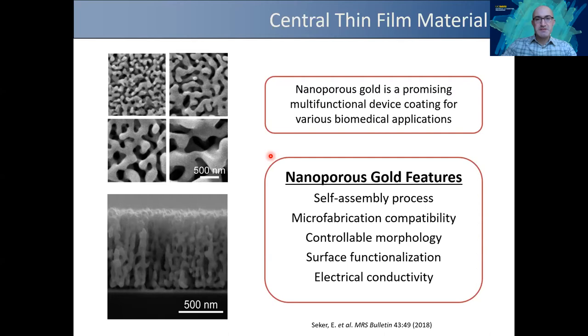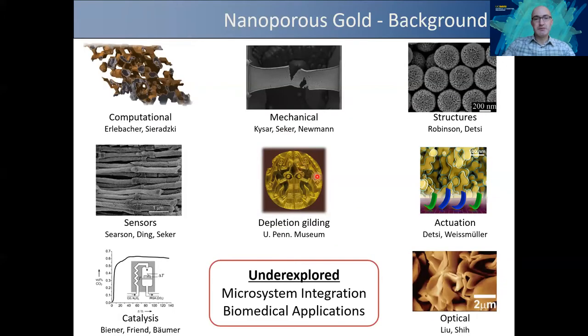All right, so a brief history about the material. It's nothing new. It actually dates back to pre-Columbian times, where Andean goldsmiths used a technique called depletion gilding. The material was a gold-copper alloy called tumbaga, which is found in many of the artifacts from that area. It has robust mechanical properties, but it did not have the gold finish. So the Andean goldsmiths leached the copper from the surface and compacted it to make a gold finish over it. At that time, as you may appreciate, access to scanning electron microscopes was pretty limited, so they were not able to witness this nice morphology that we see these days.